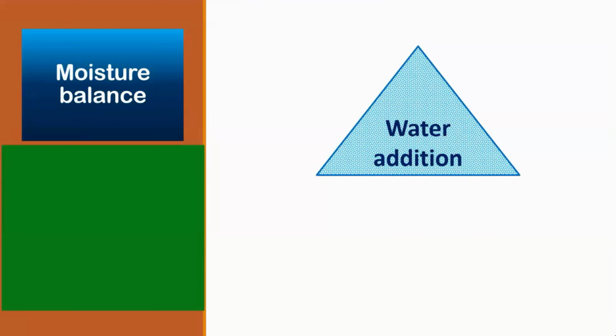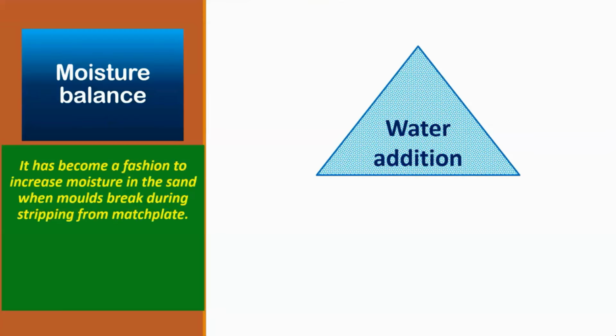We take the next step of rejuvenating, that is moisture. So there is a balance of moisture in water addition. See, whenever there is a mold breakage, there is a tendency to increase the compactability. That means a fashion to increase the moisture. It works sometimes, no doubt.